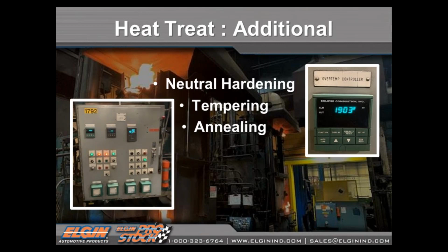So tempering is done typically on cyclic parts like kingpins, piston pins, cams, anything where it's going to see a lot of cycles up and down in service. Tempering is done at low temperature, so it's between 300 and 400 degrees F usually.